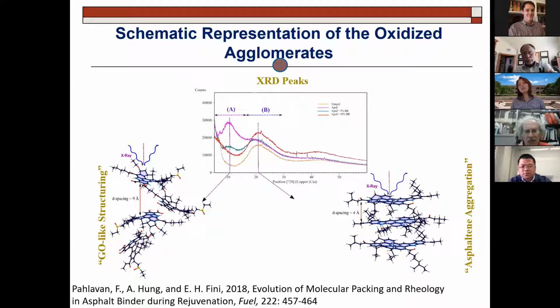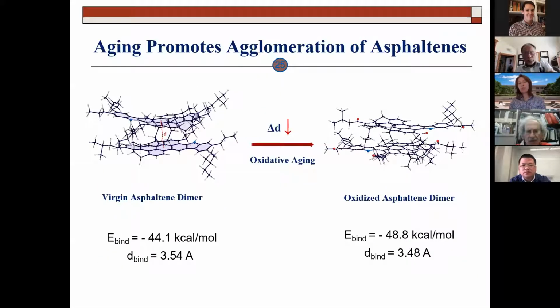When asphalt ages, it oxidizes and the molecules agglomerate, they bundle. This is the XRD picture that shows the peak moving toward the left, but in a simple schematic, you're going to get a bundle of agglomerated asphalt molecules, and that's aged. There's also a picture on the energy side. When you have two unaged asphalt molecules, the interaction energy is 44. As soon as they become a bit oxidized, it becomes 48. That means they're going to attach like magnets, more and more and more.